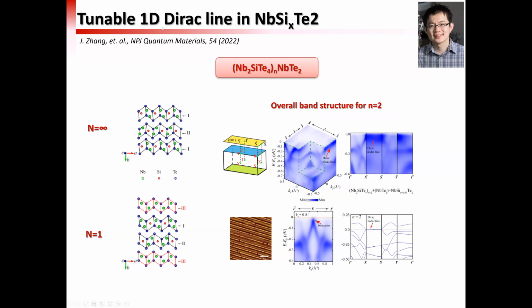We have tunable 1D Dirac lines in niobium silicon tellurium x, 2. Basically, the concept is pretty straightforward. You can see that this material is made up of building blocks niobium silicon tellurium and niobium tellurium 2. The niobium tellurium 2 layer is conductive, and the other one is not.